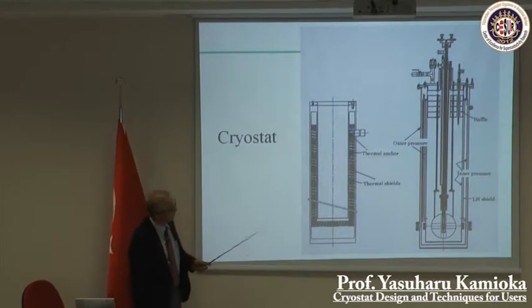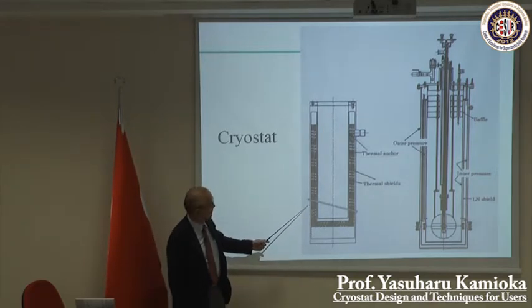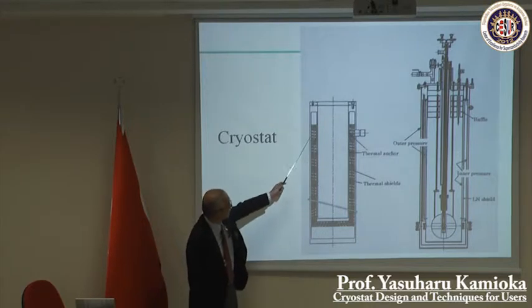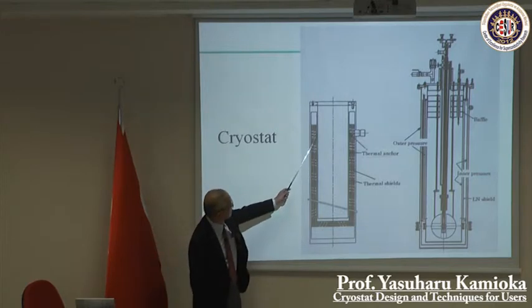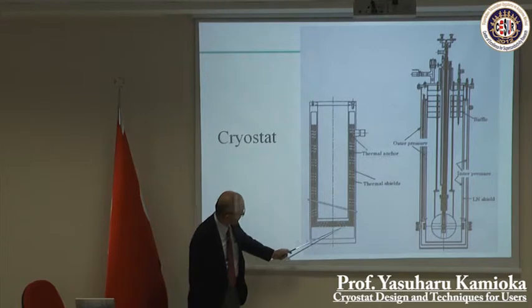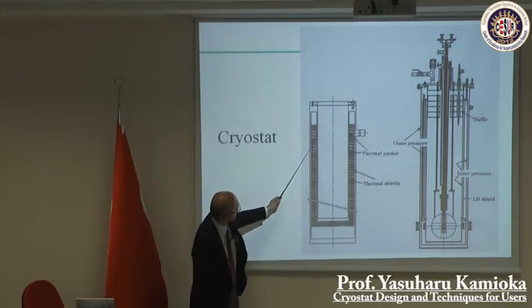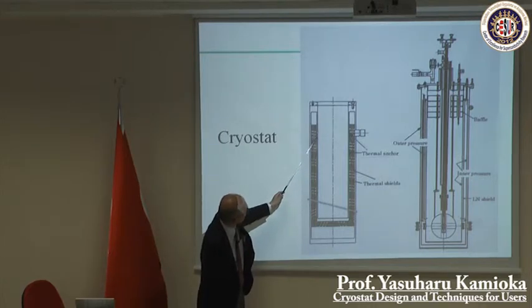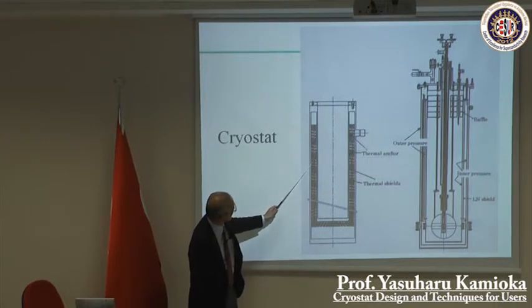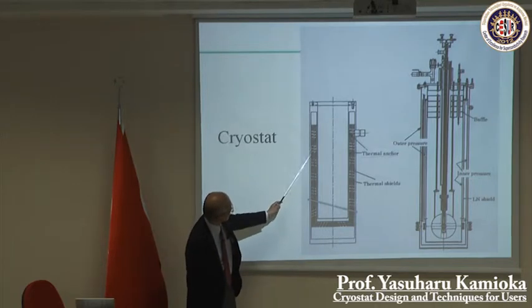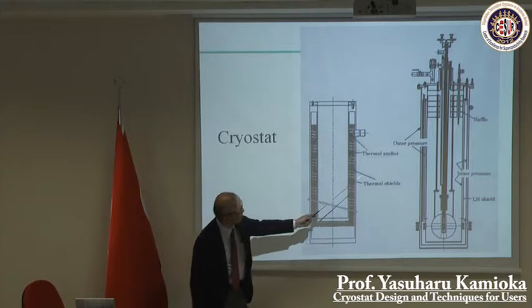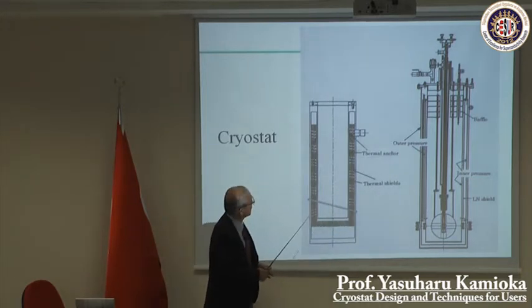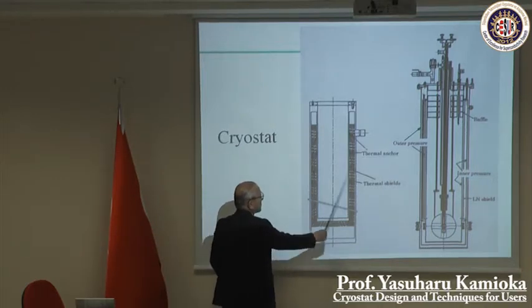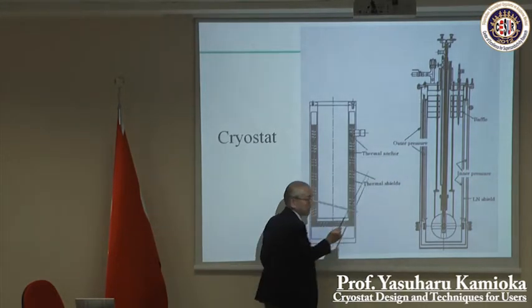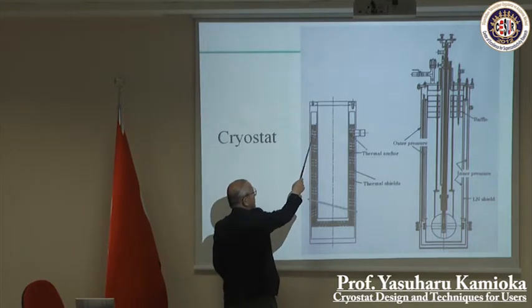And this is also again a cryostat, but this is a plastic type cryostat for liquid helium. There is no liquid nitrogen chamber, but you have a cold shield outside, cooled by neck through cold gas, so that we have two shields. This temperature is about 30 Kelvin, and this temperature is 180 Kelvin. So they are almost the same as this nitrogen chamber here. But we cannot use this technique with stainless steel because there is too much heat from the top. This is plastic, so heat from the top is very small, so we can use this.